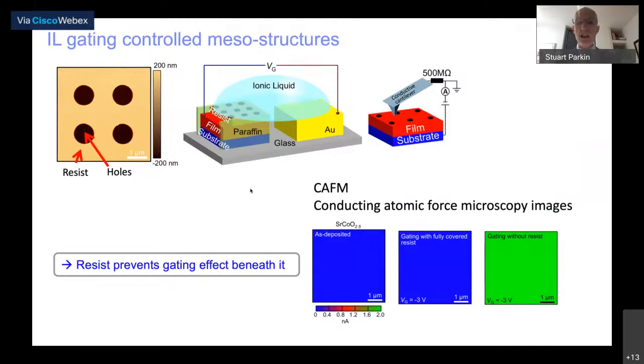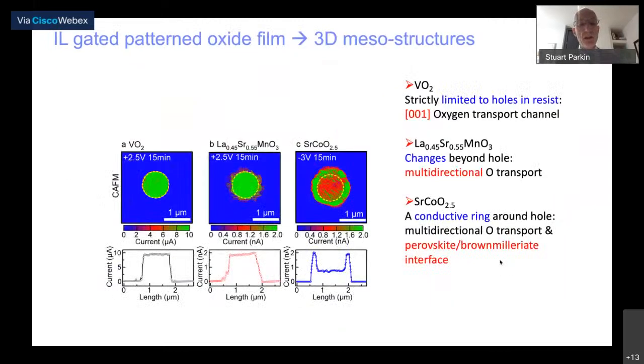So what we do is take a film of strontium cobalt oxide, put a resist on top, make holes in the resist, shown as these black holes, and then gate through the holes. This shows that if we take SrCoO2.5, which is insulating, we see no current in a conducting atomic force microscope. If we cover it with resist and then gate, nothing happens. And if we use no resist and gate, it becomes green, very conducting, as we switch from the insulator to the ferromagnetic metal.